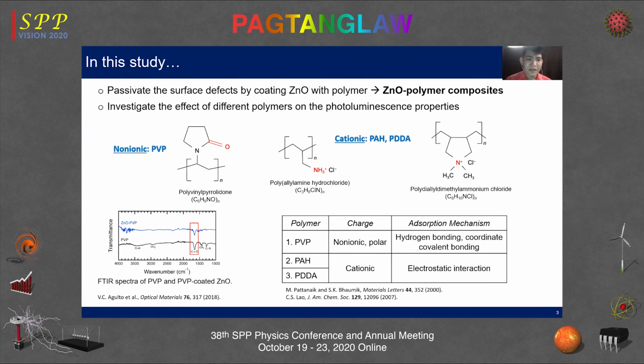We used three different polymers. One is non-ionic PVP or polyvinyl pyrrolidone, a cationic PAH or polyallylamine hydrochloride, and a high charge density PDDA or polydiallyldimethylammonium chloride. Polymers can interact with the ZnO surface through functional groups. For PVP, the carbonyl group can interact with ZnO through hydrogen on the surface by hydrogen bonding or zinc on the surface by coordinate covalent bonding. On the other hand, PAH and PDDA are polyelectrolytes and they will dissociate in an aqueous medium, making them charged.